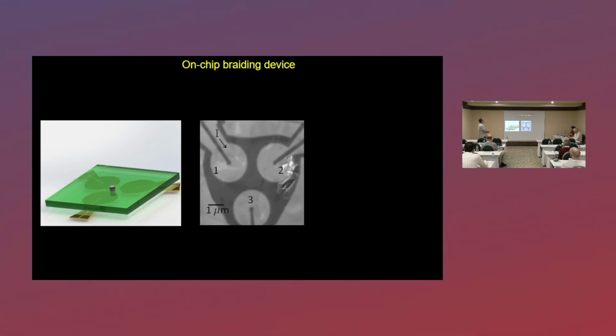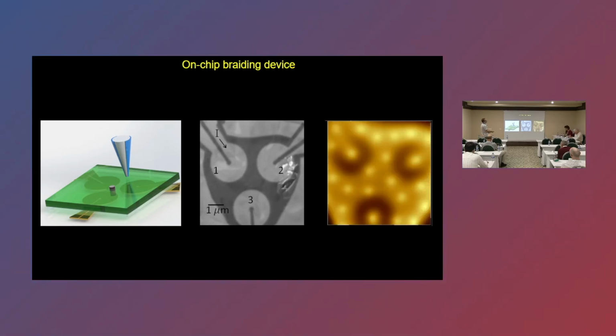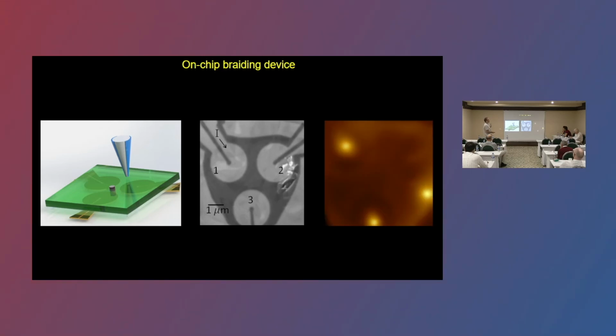And the idea is that you can put vortices in this layer, and maybe you can manipulate them. The idea here is that we use our microscopy technique not to move vortices, but only to image, to validate our design. So if you cool down at a certain field, you see here a bunch of vortices, and you see here exclusion zones, okay, where there are no vortices, and that makes sense because there the vortex needs to thread through 2 superconductors. But what you see here is that there are 3 vortices at the 3 central points of these loops. And if I cool down with a lower field, I can get just a few vortices.